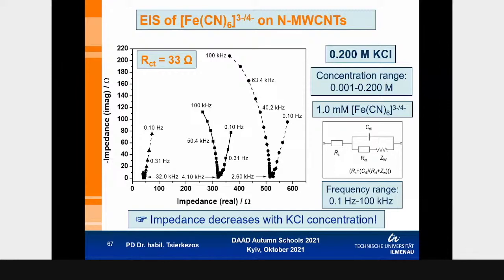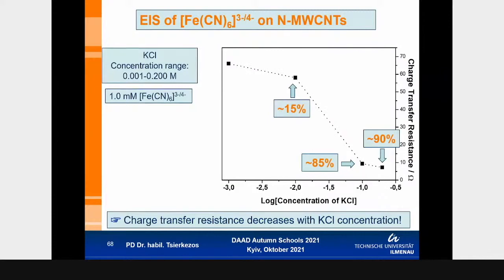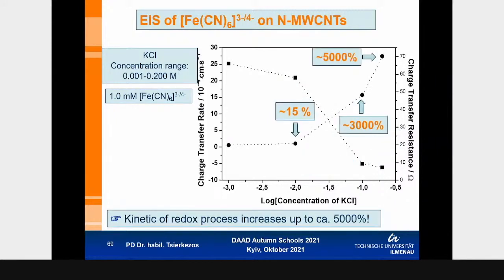concentrated KCl solution. You can see also here that the charge transfer resistance, the barrier of the electrochemical reaction, decreases up to 90% if we increase the concentration of the KCl from 10^-3 up to 0.2 mol per liter. Also, the kinetics increases significantly, I would say, with the increase of the concentration of the supporting electrolyte. So please note that when you use such systems, you have to increase the concentration of the supporting electrolyte in order to get a reversible behavior.